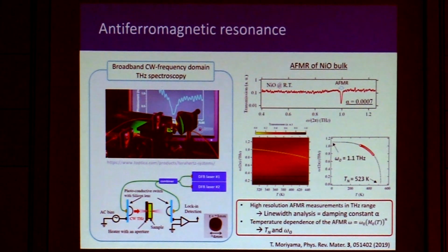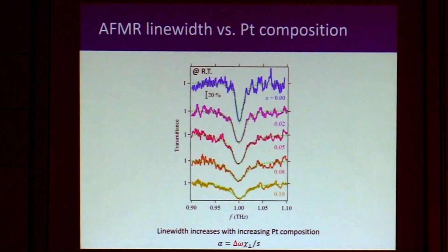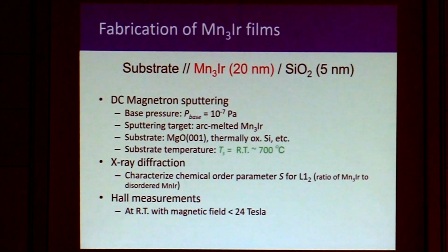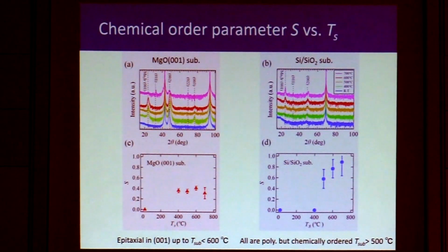For your experiment with your thin films, have you checked the crystal structure of your actual thin films? It's a highly textured film on magnesium oxide. It's an L12 FCC structure, like the manganese 3 iridium crystal structure. But it may have some strain, like a distortion. It won't change the crystal structure, but we haven't characterized that.